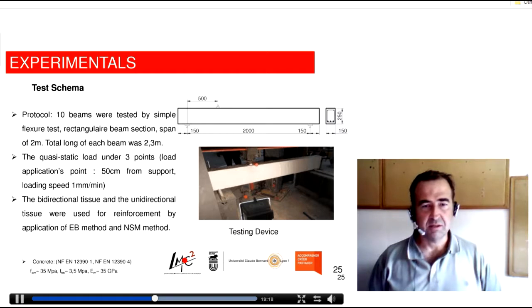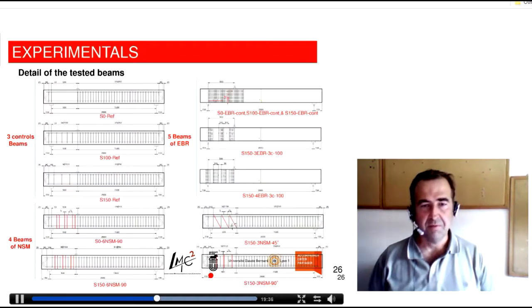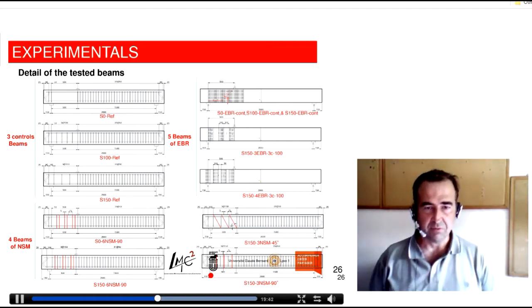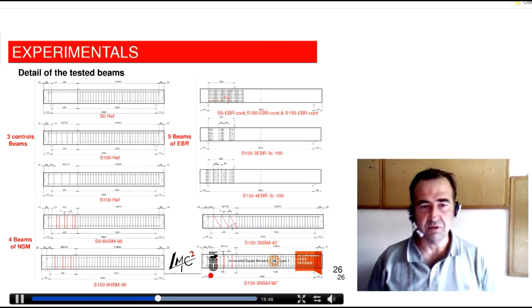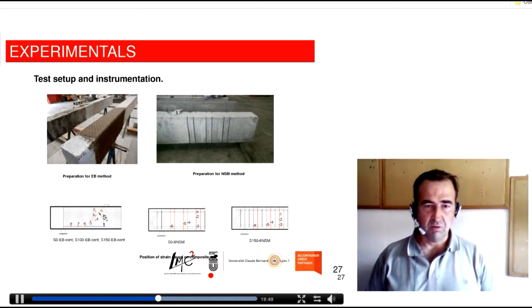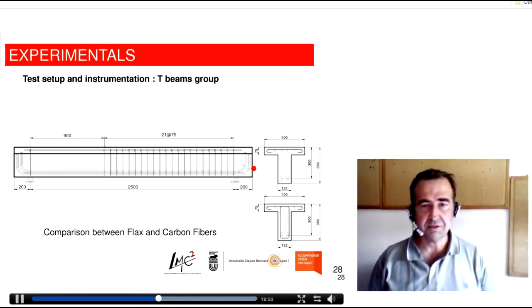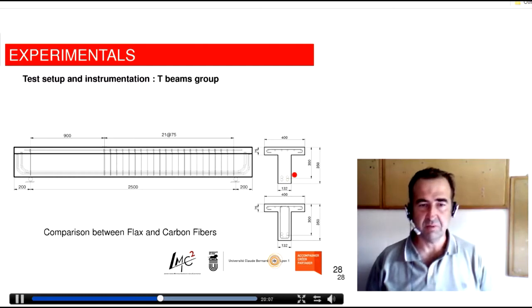We didn't focus on different inclinations or NSM techniques. So, more details about the specimens we test. Ten beams, 2 meter span, have been tested, loaded in this way, such that we have a high level of shear loading in this area and less in this one, so that the shear failure occurs here. You have all the details about the strengthening in this slide. Of course, more detail can be obtained if you just send me an email. We also evaluated the T section. For this one, it was a 2.5 meter span, and the idea was to see about the problem of debonding and to get a higher depth beam in this area.